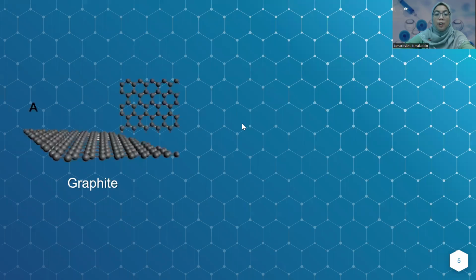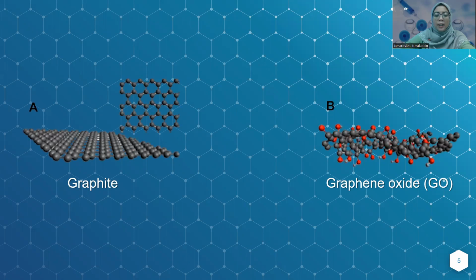Besides producing graphene from graphite, graphene oxide can also be produced from graphite. Graphene oxide, as you can see in B here, can be produced from graphite by the exfoliation method. Graphene oxide is a derivative of graphene that has been functionalized with oxygen-containing groups. In figure B here, we can see that the red balls represent oxygen-containing groups. When graphene oxide has the oxygen-containing groups, it makes graphene oxide easier to disperse in solvent and manipulate for certain applications.